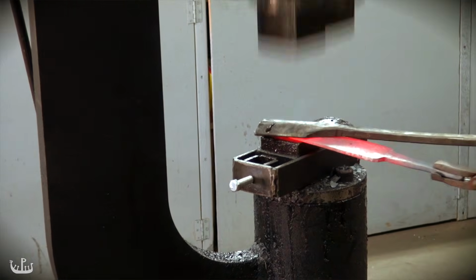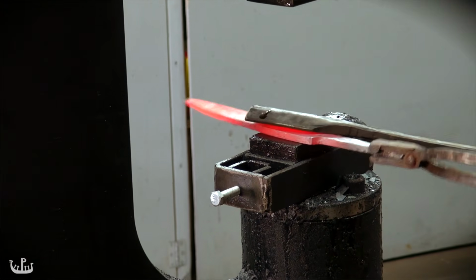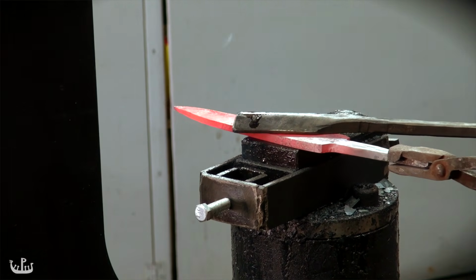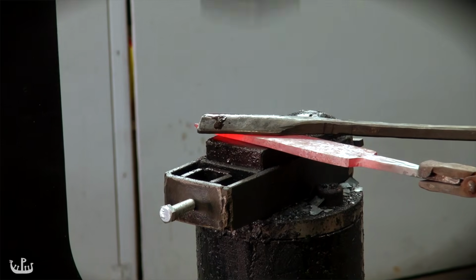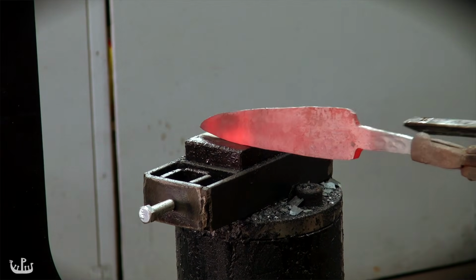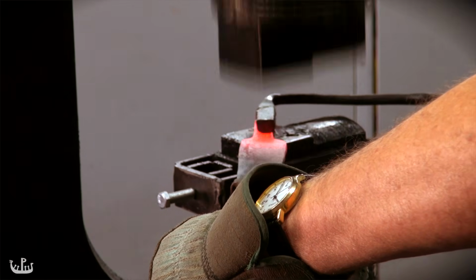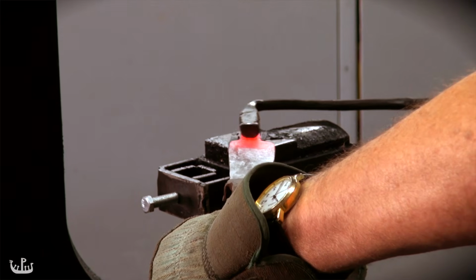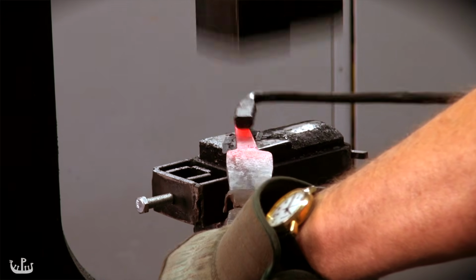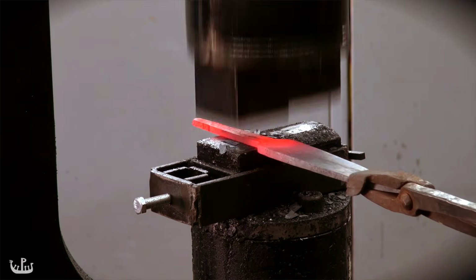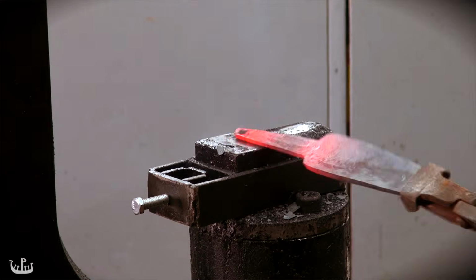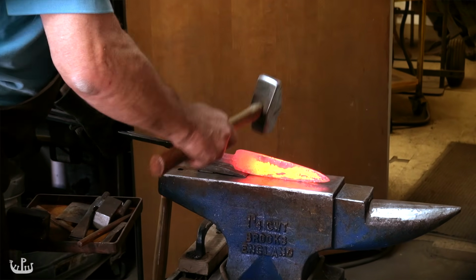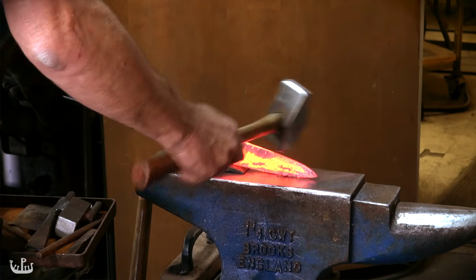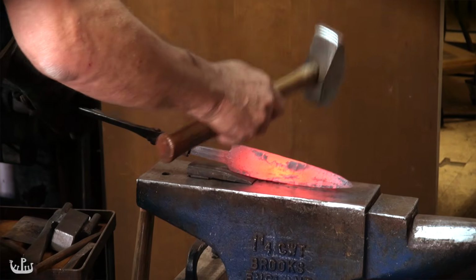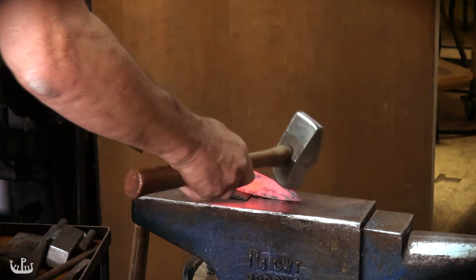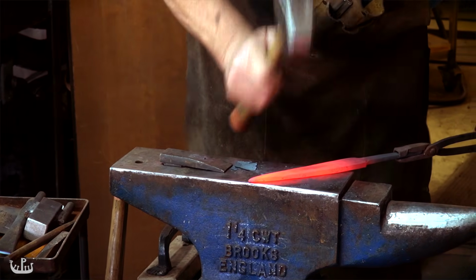Now we slowly bevel the cutting edge. As mentioned previously, the steel needs to be worked at much lower temperatures than traditional steel. Wootz steel is ultra-high carbon steel with impurities such as vanadium, around which carbides segregate and form visible patterns. We aim for a blade width slightly larger than 1.5 inches and continue to forge the blade so that the cutting edge smoothly tapers into the point.